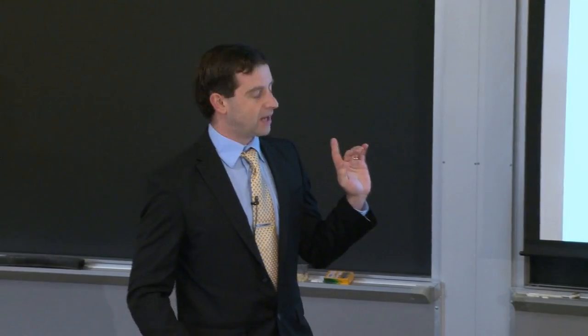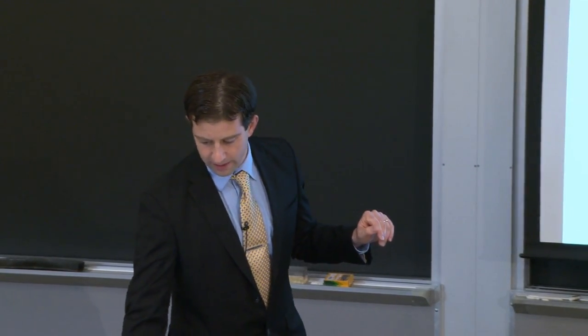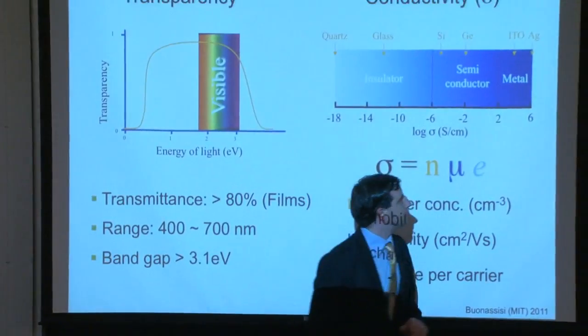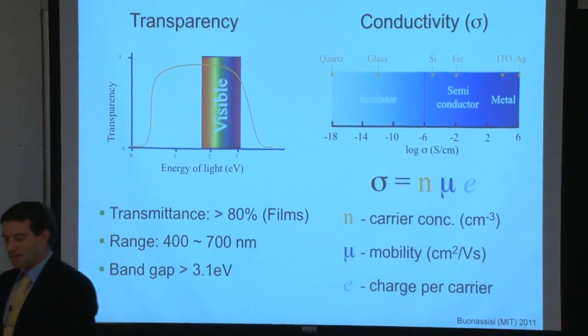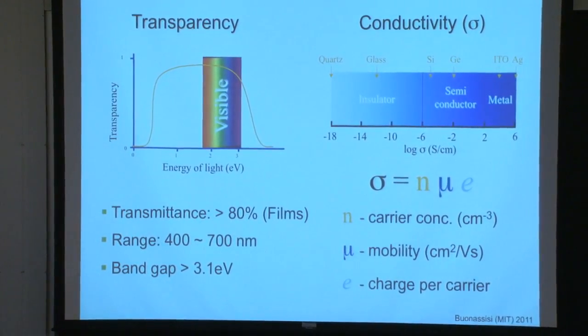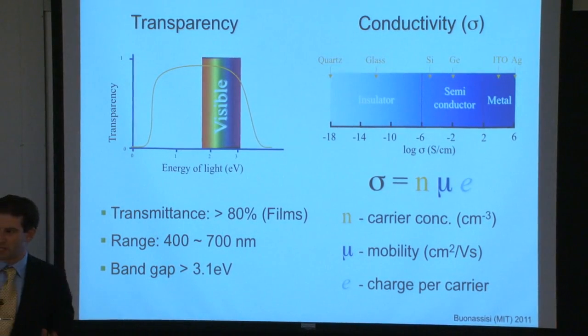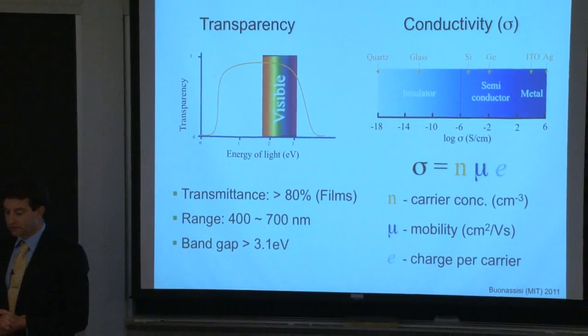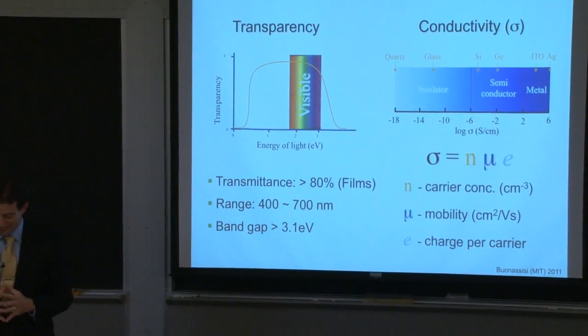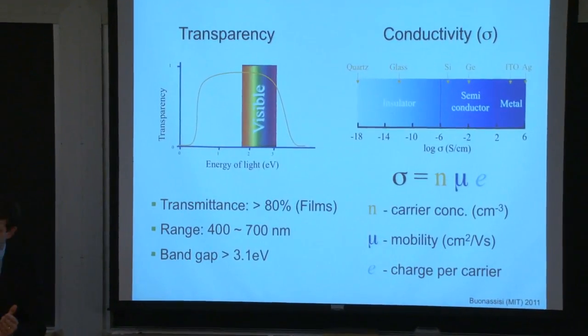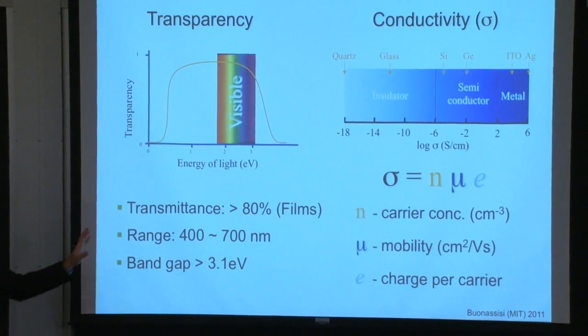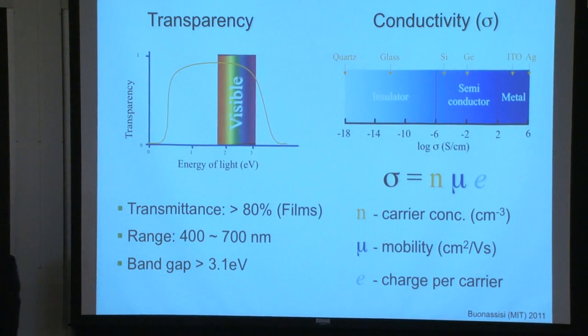And because ITO, or indium tin oxide, is just so amazing in terms of its conductivity, it's almost up there buttressing against silver, it's very difficult to replace with something else. Zinc oxide and its variants get pretty close, like aluminum-doped zinc oxide, sometimes called AZO in the PV community. They get pretty close, but they're not quite as good in terms of optical transparency and conductivity as ITO.